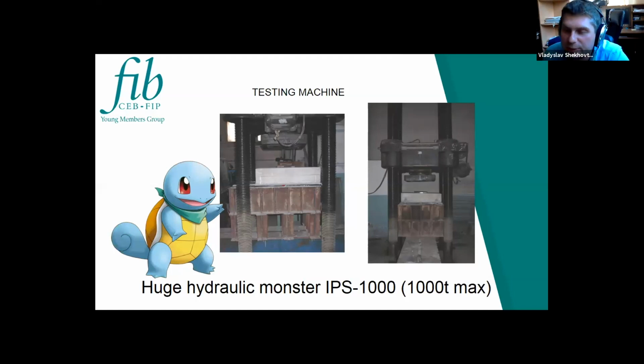Plates were supported by the perimeter, so the upper part was stable and the pressure goes from the lower part. So we have an upside down situation, but in such a frame we can see the bottom surface of a plate, fix cracks, and take values from gauges, so it is possible to perform this experiment.